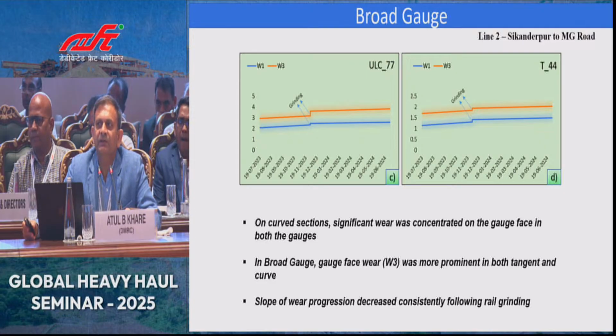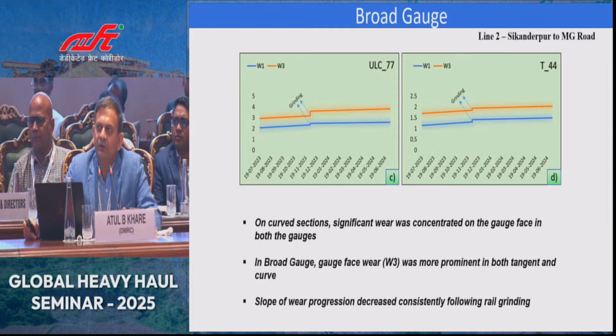So this ULC_77, which is shown in the slide, is on broad gauge sharp curve. You will see that the vertical wear rate we are measuring is substantially high, whereas the wear on gauge face, the vertical wear is being presented in the blue line and the wear on gauge face is being shown in the orange line. So on broad gauge, the sudden spike which you see on this slide is the grind cycle. So you see the wear rate after grind cycle in both the cases on broad gauge, on sharp curve, has reduced. Second picture is on the tangent. There also the wear rate has reduced.